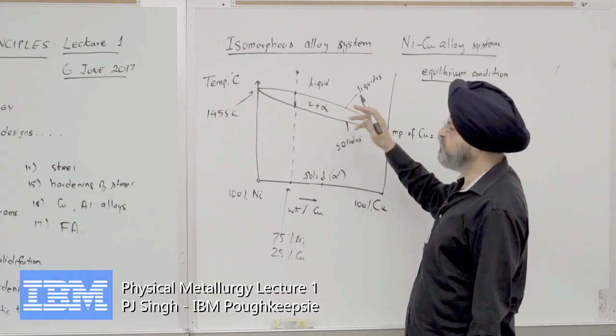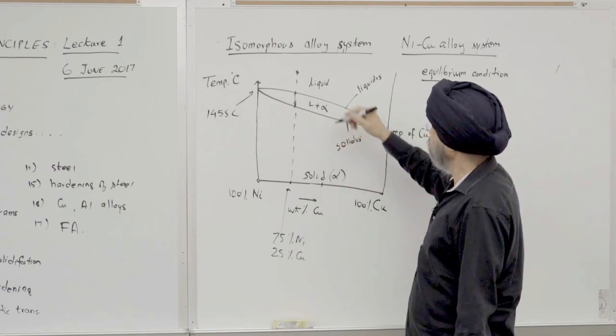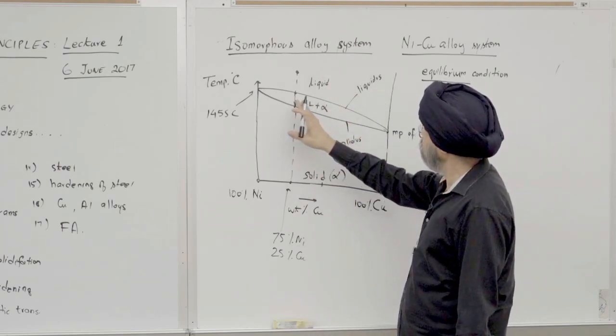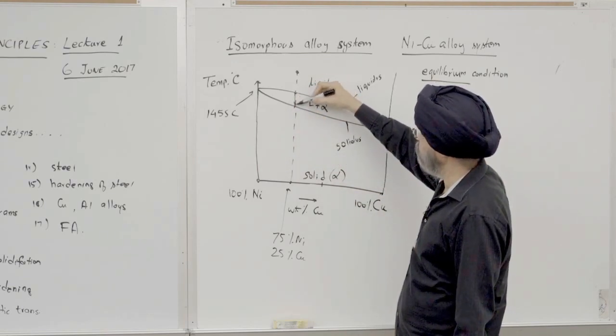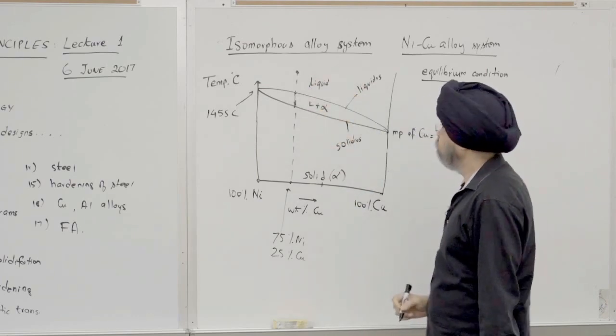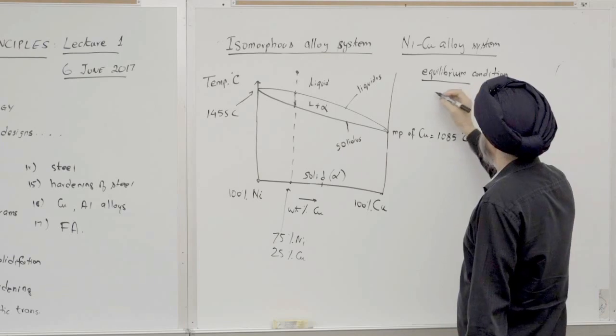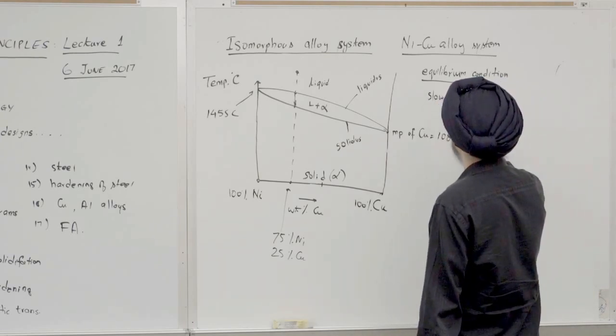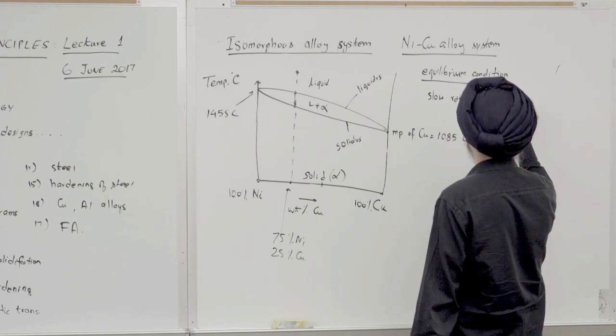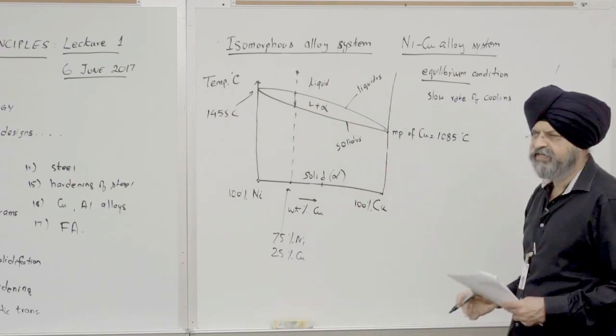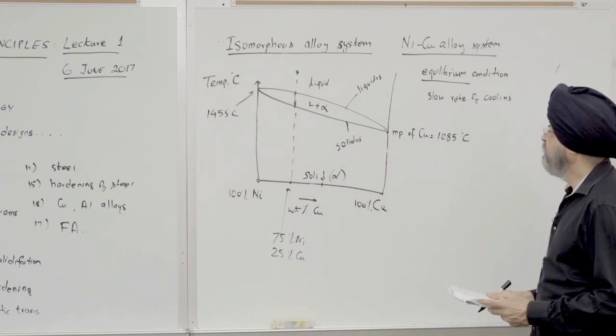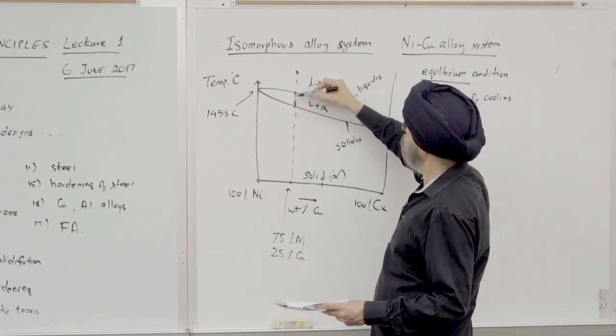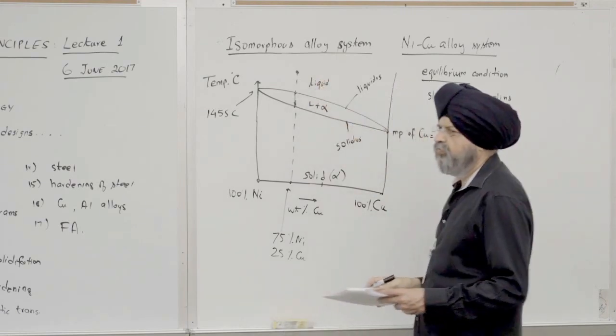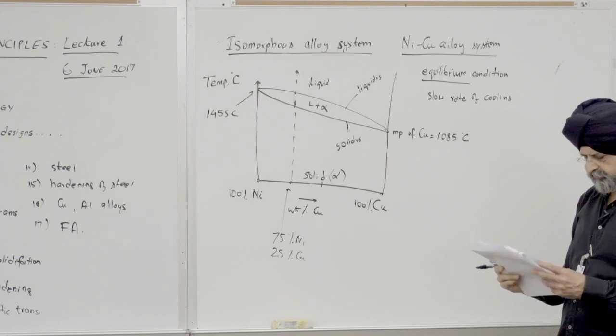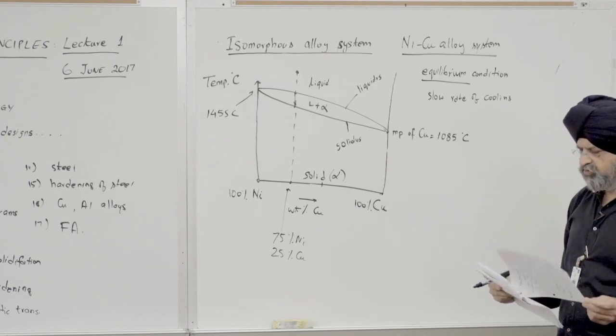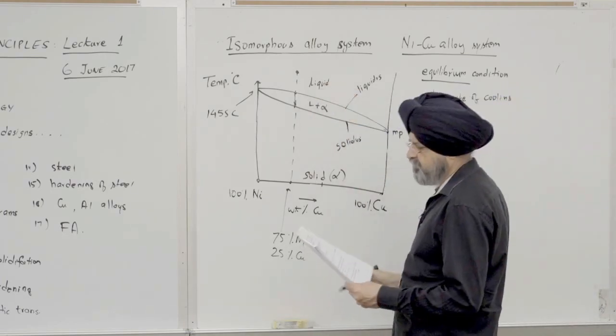But this is under conditions of very, very slow cooling. If I cool fast, then I don't get the reactions happening at these temperatures. The temperatures decrease. So equilibrium conditions means a very slow rate of cooling, or if you're going from room temperature, a very slow rate of heating. That's a very important thing, because when you look at phase diagrams and think of these temperatures, we have to remind ourselves that we're dealing with a very, very slow rate of heating and cooling. So we have to allow sufficient time for the reactions to happen.